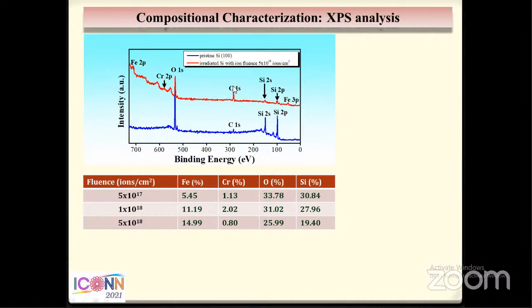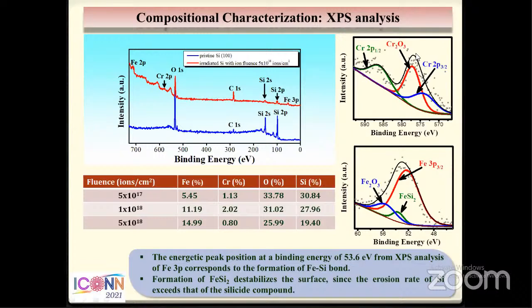and that is due to the co-deposition of the sputtered material from the stainless steel target on the silicon surface. And this is the atomic concentration of various elements on the silicon sample. Also, we have performed a core-level analysis for the highest value of fluence.